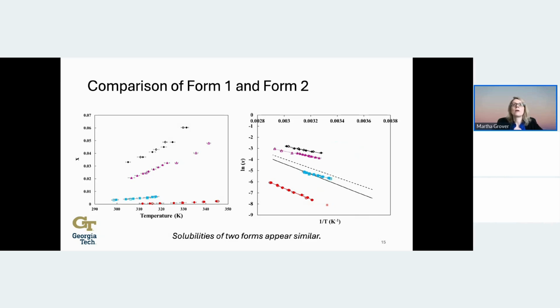And we can compare forms 1 and 2 here. And so we can see that because we had a different heat of fusion for form 1A and form 2, in melting temperatures these ideal limits are slightly different. But actually, the measured solubilities for form 1 and form 2 are virtually the same. It's really hard to say that you could distinguish them. You could look a little bit, that maybe there's a different offset here and maybe some difference here with the alcohol or not. But I would argue that we cannot say that these forms are different based on the solubilities.